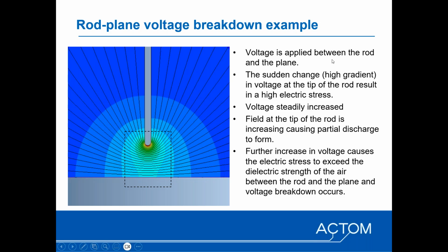Now I've got a video that I can quickly show of the phenomenon of voltage breakdown. The setup is that we've got the rod at the top and the plane at the bottom, and when the voltage is applied, you've got the discharge happening on the actual electrode. As the voltage gets increased, more corona will form, more partial discharge will form, up to the point where the medium between the electrodes cannot withstand it anymore, and a physical breakdown will happen. So that's effectively the mechanism for having breakdown due to the high field stress.